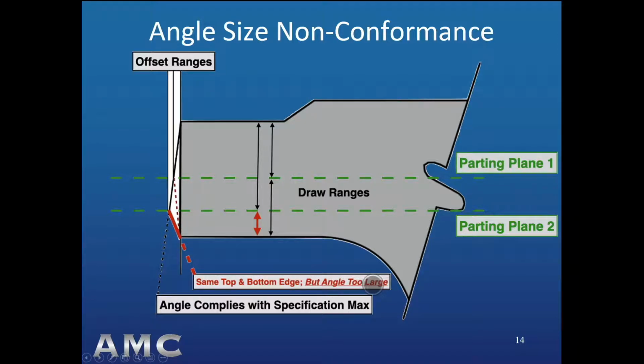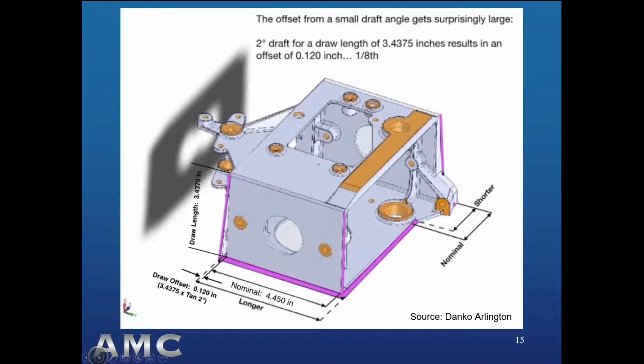That angle maximum violation may be called out as a dimensional nonconformance in the first article test. Here is a real DLA casting that suffered a first article test nonconformance involving draft. It is an aluminum structural casting for the T-38 airframe. In the next slide, the allowable 2-degree draft is shown in dark pink, resulting in the bottom of the end feature being out of tolerance on the left side. On the front of the casting, the same amount of draft offset causes a low dogleg feature to be out of tolerance on the short side.